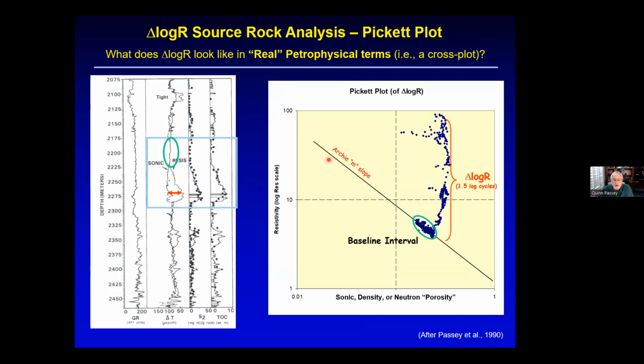It doesn't follow all the things that they had been taught at university. But if you plot it on a resistivity versus kind of a porosity plot, the baseline intervals form a line with an Archie slope of M, just like with conventional reservoirs. And the delta log R separation shown by the red arrow plotted in a cross plot would show up as an increase in resistivity above that line. So it does kind of fit the same kind of analysis, but there's so much more information that we can see from the overlay, the thickness, how it's changing, and we can better understand the geological environment and how it relates to other reservoirs.